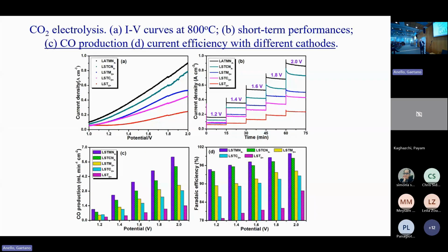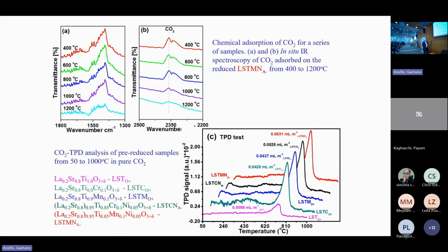So to the right, you get high carbon monoxide production from these systems. And again, if we look at temperature programmed reduction, you see the sample with the best performance has got the strongest CO2 absorption. So absorbing the CO2 at the surface is key. And again, in the IR, you see that the peaks are much enhanced with manganese.